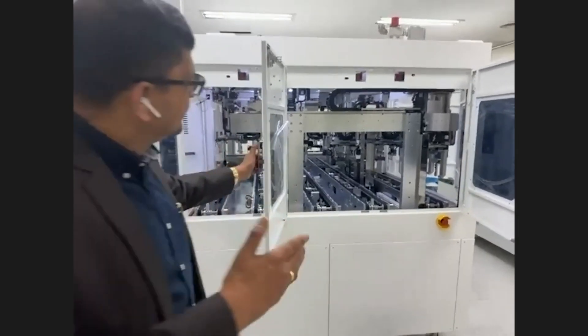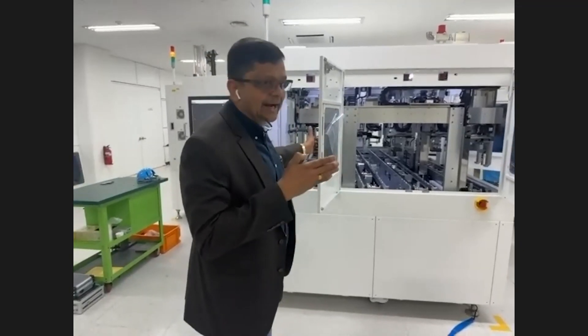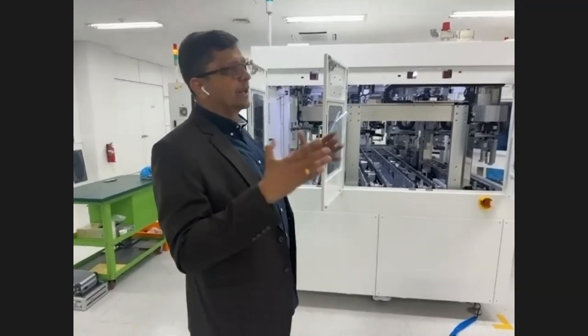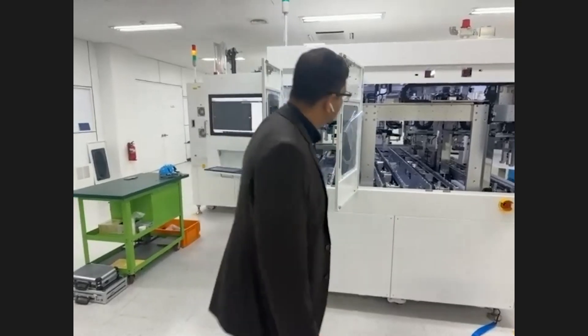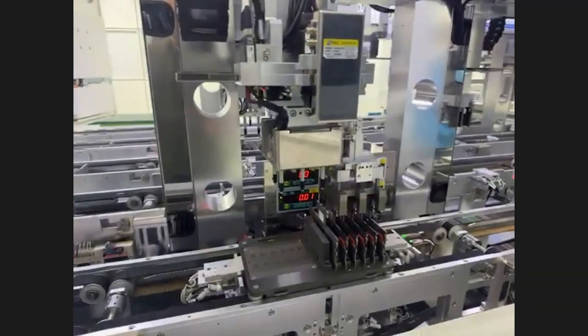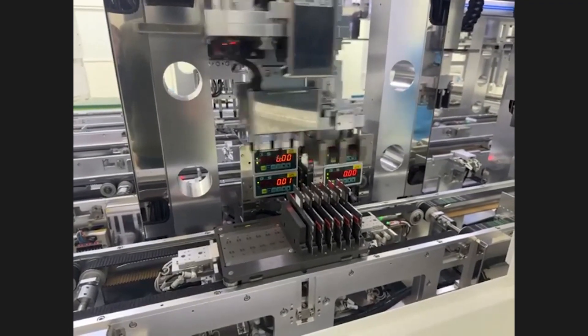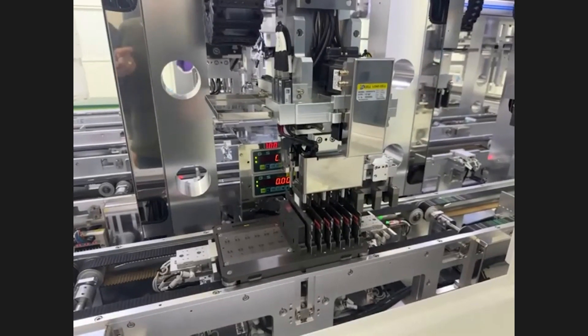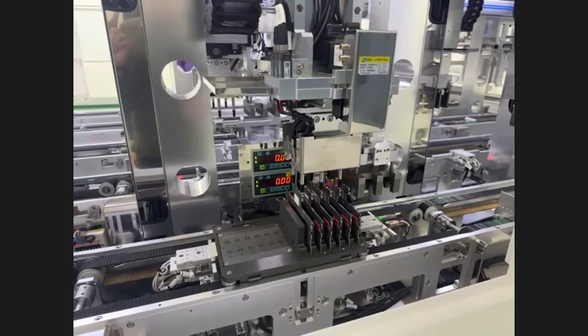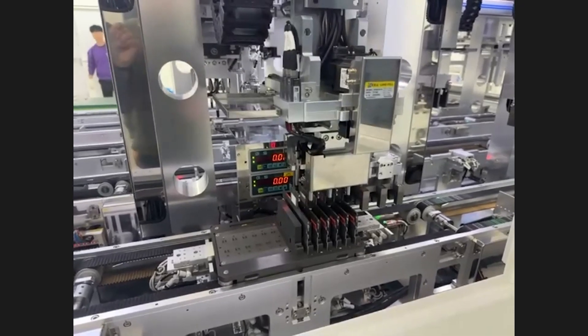When the stack is done, we need to measure absolutely how the stack is straight and exactly lined up, so there is no chance of shorting between a cathode and anode. This is being done here on this machine, and we're going to show it operate now. You can see the six stacks coming from the stackers are fed into this machine, and every stack is measured using lasers to make sure that the C2A dimension, which is very critical, is met.